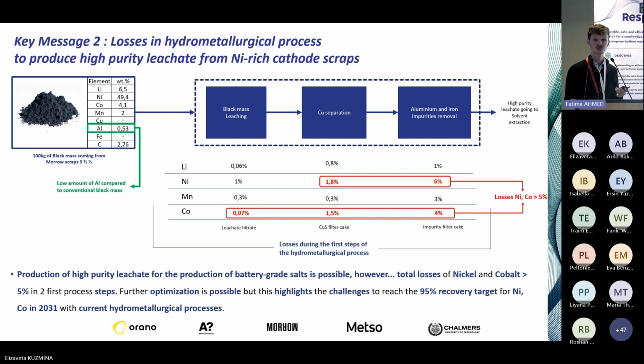Good news is that we reached the 90%, which is set in the legislation for 2027. But the 95% might be challenging in the future for recyclers. Of course, it is only a first pilot test result. We still have 2 years in the project to further optimize the process and improve this recovery and reduce the losses in the hydrometallurgical process.